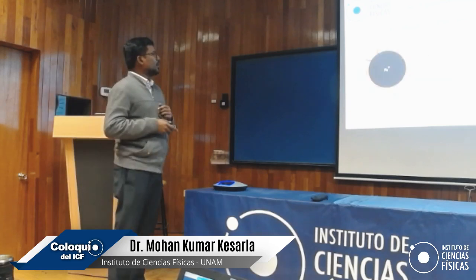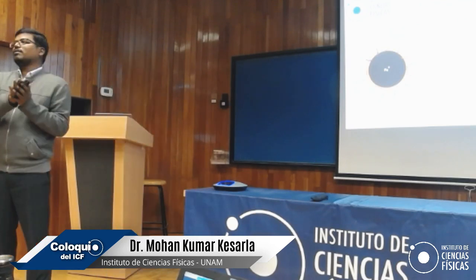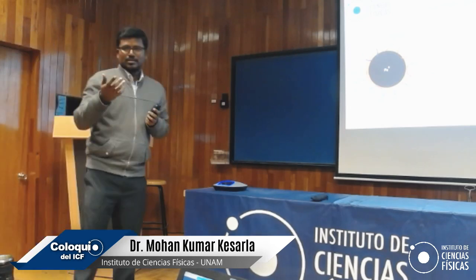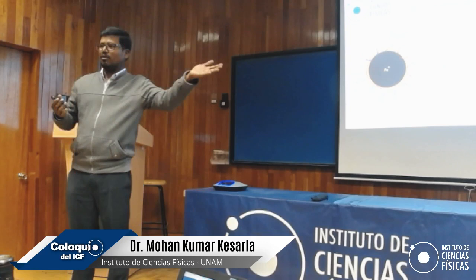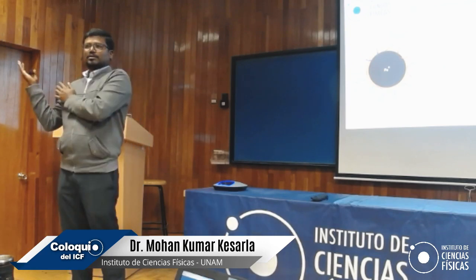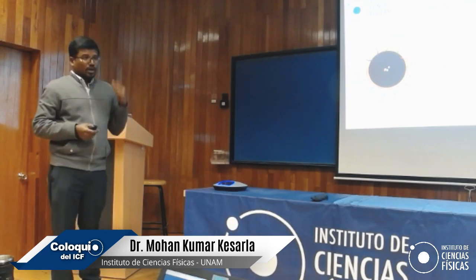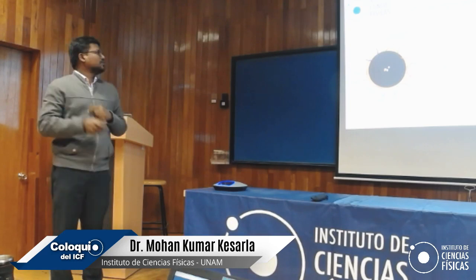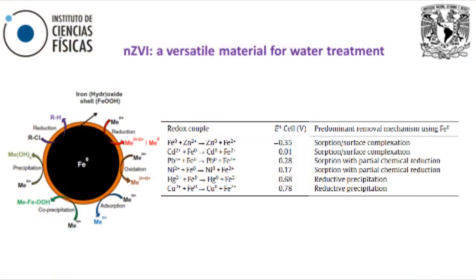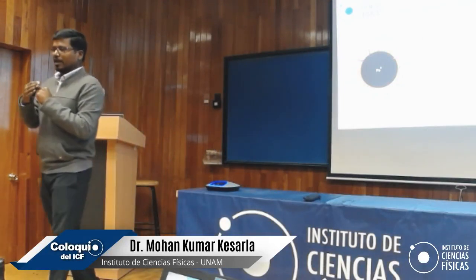Looking at zero valent iron, as I told you, if iron is in zero valency, it tends to convert into its stable form, either Fe2+ or Fe3+, very fast. If you take bare zero valent iron and subject it to oxygen, it will immediately ignite and convert into either ferrite or magnetite. So that's a problem. But if you control the process parameters, you can at least manage the zero valent iron with a shell of iron oxide or iron oxyhydroxide. Whether the formation of a shell on zero valent iron is a good thing or a bad thing, we'll discuss later.